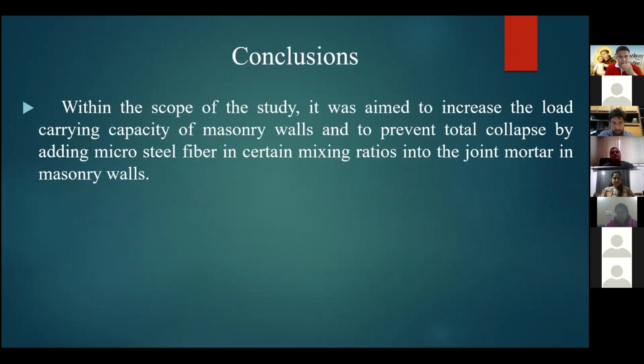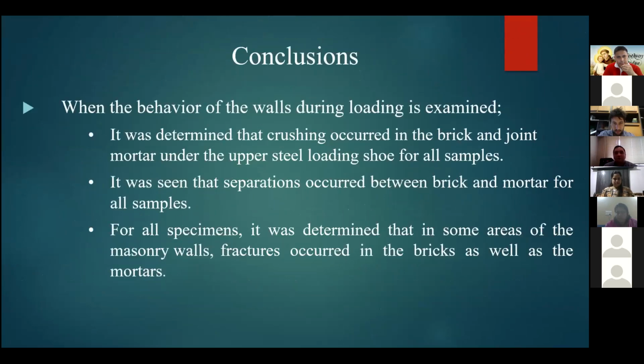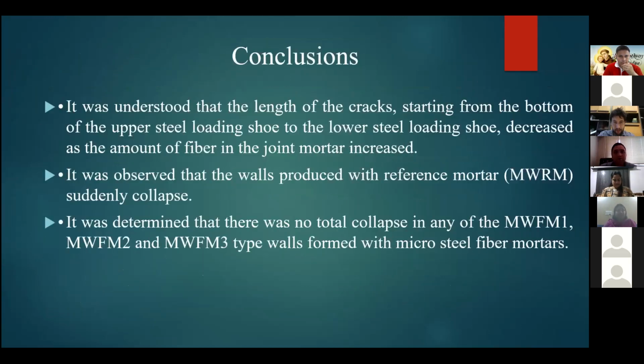Conclusion: within the scope of the study, it was aimed to increase the load carrying capacity of masonry walls and to prevent total collapse by adding microsteel fiber in a certain mixing ratio into the joint mortar in masonry walls. When the behavior of the walls during loading was examined, it was determined that crushing occurred in the brick and joint mortar under the upper steel loading shoe for all samples. It was seen that separation occurred between brick and mortar for all samples. For all specimens, fractures occurred in the bricks as well as the mortar in some areas of the masonry walls.